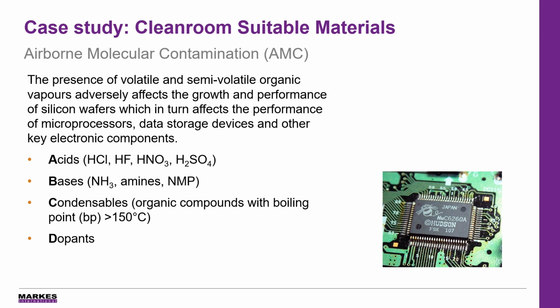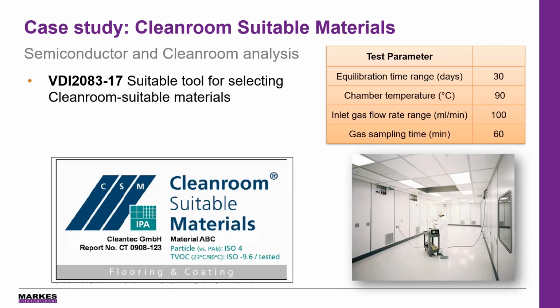Sources of the VOCs that affect semiconductors is actually the materials that the clean rooms they're manufactured in are constructed of. So there are some regulations and standards for the quality of that material. And one of the methods shown here, this is a German national method, utilizes the microchamber with an elevated temperature of 90 degrees to force those emissions, so that we're looking at this very low emitting material. And it gives it what's called a clean room suitable material standard mark. And this gives manufacturers an understanding to be able to choose the lowest emitting material.